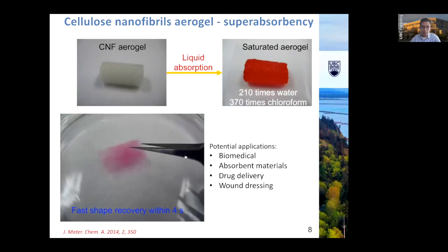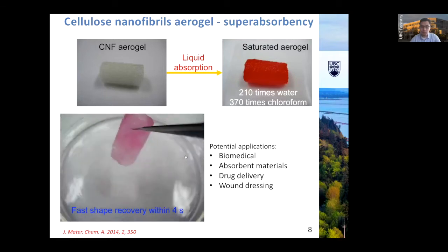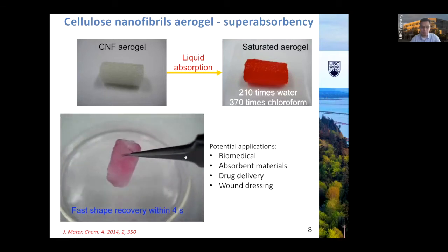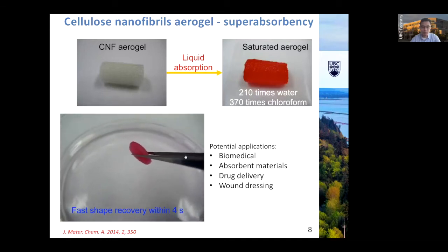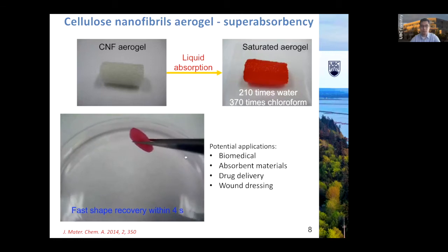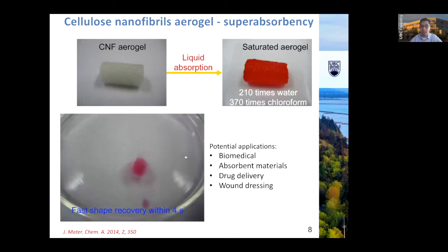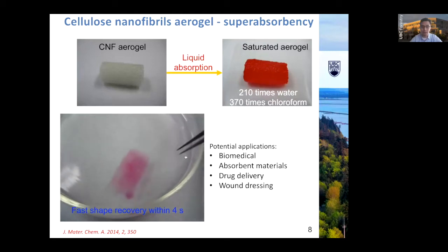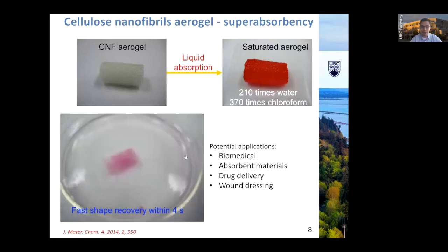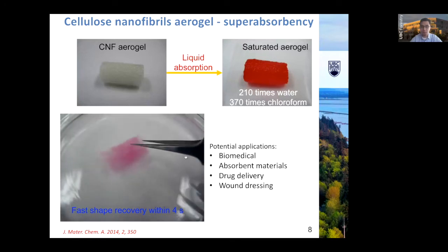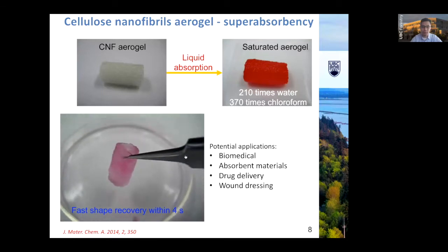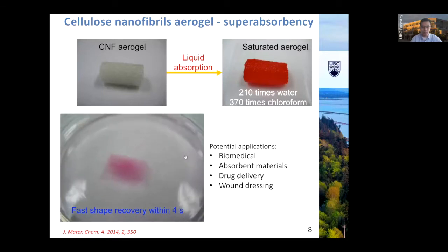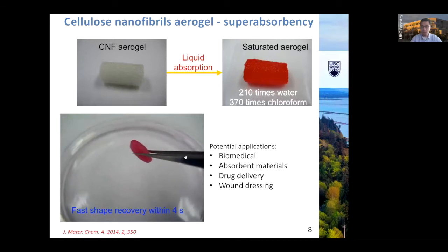It should be noted that this aerogel is 100% cellulose. We do not use any chemical cross-linker, so mostly it's by hydrogen bonding. All the strong structure is formed by hydrogen bonding due to the ice crystal templating. This is only due to the very high surface area of the nanocellulose. You could not achieve this if, for example, you use pulp fiber, which would very easily scatter once you put it into water. But due to the nanocellulose's very high surface area and a lot of surface functional groups, carboxyl group, hydroxyl group, it will be very strong just by physical cross-linking.